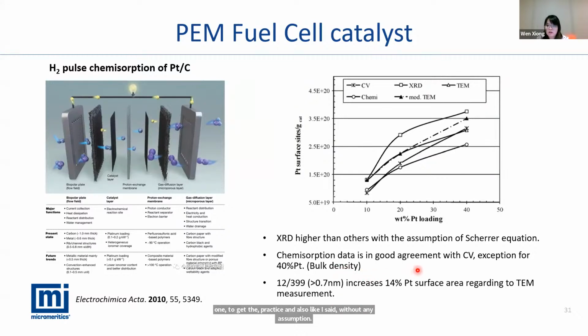And people will say, okay, the CV test should be done. Sure, I agree with that. But for the CV test, we use a very tiny sample. For example, we use 0.01 gram of sample for the testing. It's not very representative of the sample. So here I suggest using both chemisorption and CV to do the test, eliminating the test limitation of each method and getting a very good result for the concentration of surface platinum sites.